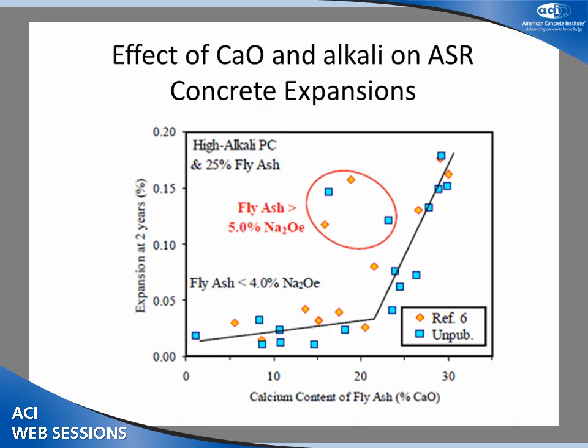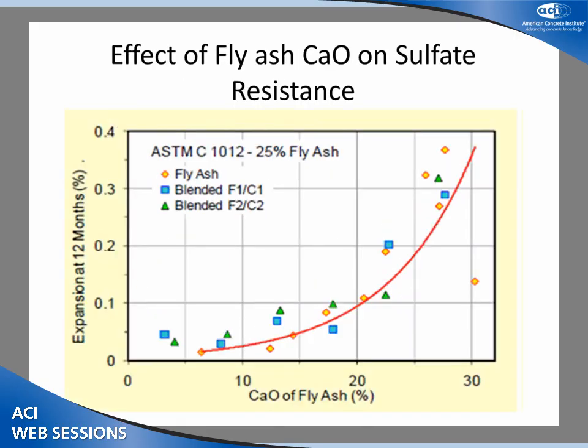So the calcium content seems to relate to the ASR control, and it makes sense because you're trying to change the hydroxyl ion pore solution concentration. To mitigate ASR, you've got to reduce the pore solution concentration of hydroxyl ions down to a level that they won't attack the siliceous aggregates. And so if you have high calcium fly ashes, you're adding phases into the system that can keep that hydroxyl ion concentration up, unless you put in a lot of fly ash. But at 25%, it's insufficient when you get to these high calcium ashes. So it's not that you can't use them, you'd have to use a lot more fly ash in that case to control it.